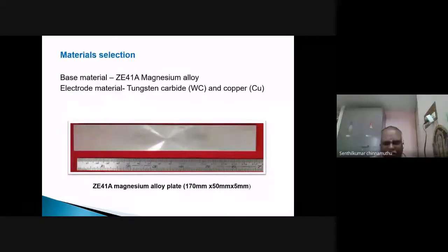The material selected for this research is the base material ZE41A magnesium alloy. Z is zinc and E is a rare earth material, that is 4% zinc and 1% rare earth material, and the remaining is magnesium and aluminum. The electrode material chosen is tungsten carbide and copper. Copper is mixed with the tungsten carbide powder to conduct electricity. So a magnesium plate of 170 mm length, 50 mm width and 5 mm thickness is taken for the electrode discharge coating.